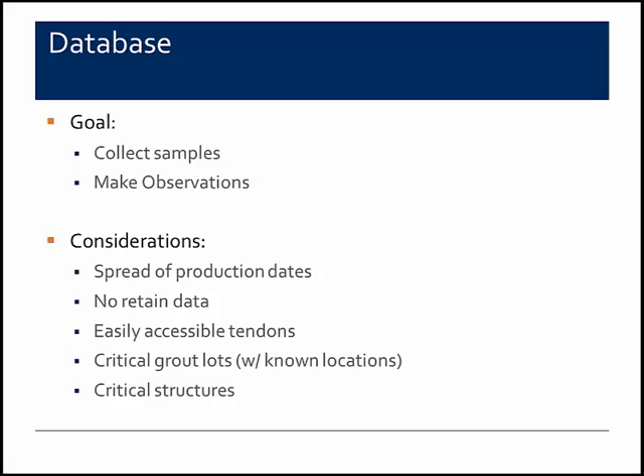One was the spread of the production dates. In general, time periods where Sika did not have retained data available, those were favored to try and fill in the database. Also, when looking at particular bridge structures, the accessibility of the tendons was considered. External tendons are generally easier to extract a sample from than internal tendons, where you might be limited to working at anchorages, if at all.